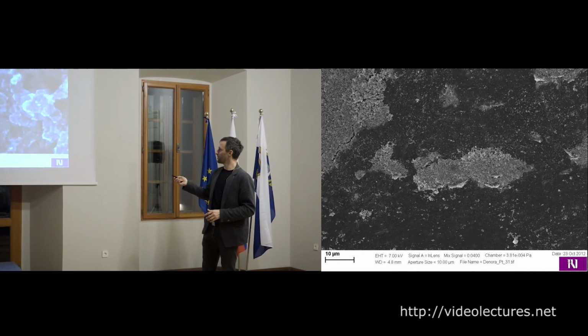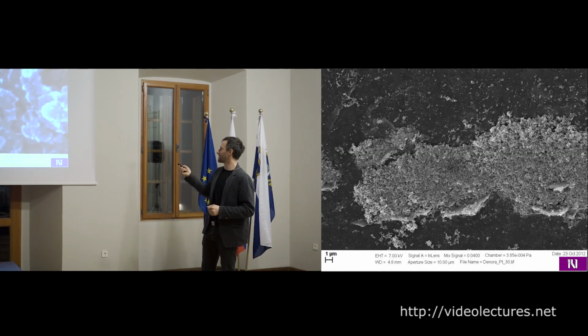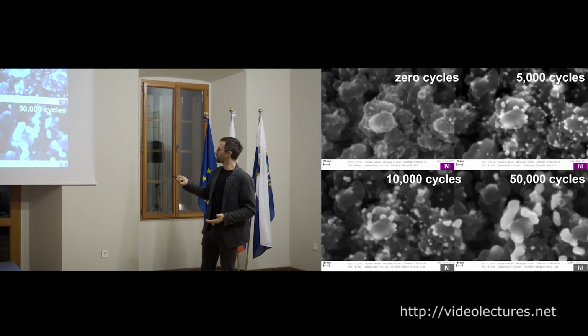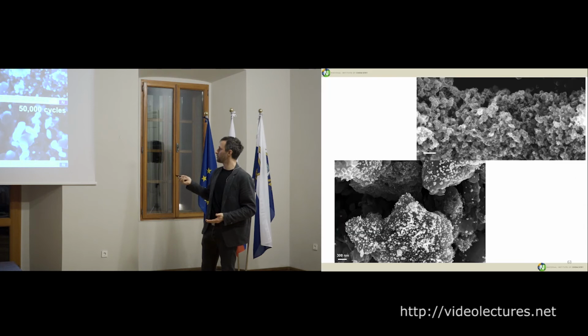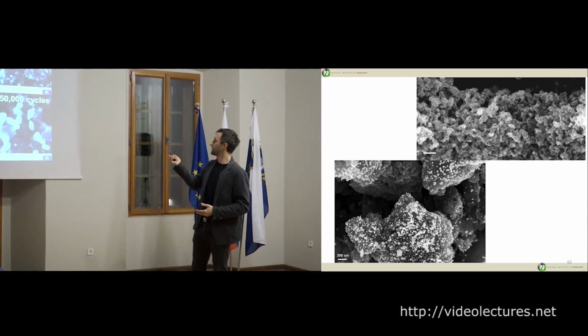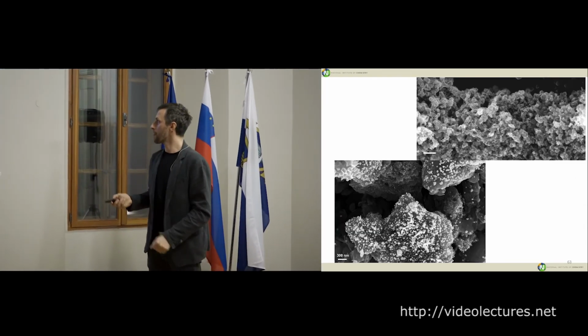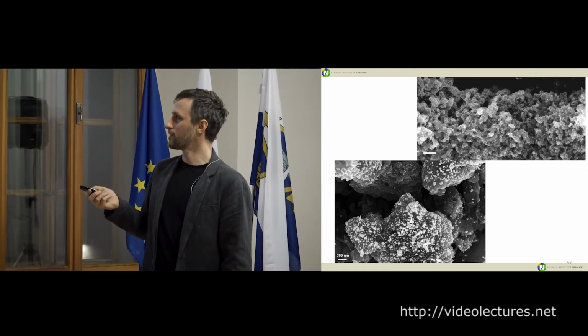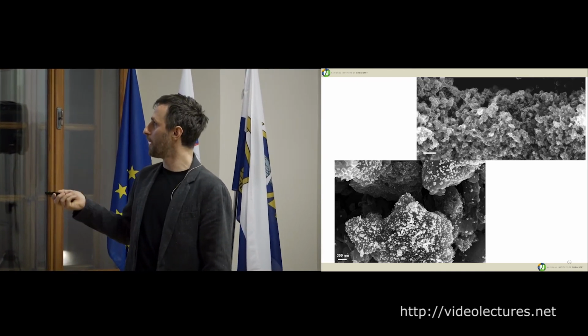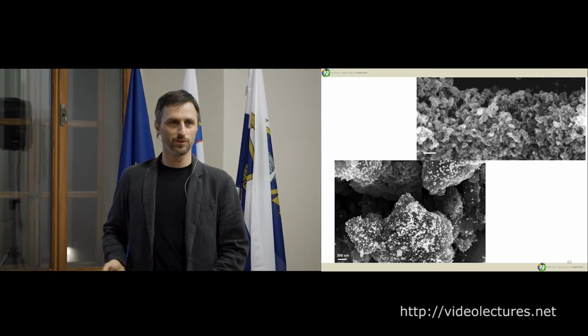Then you just zoom in, you have this path, and then in the end, it's kind of a high resolution SEM, but you see it. And then you just take consecutive images, and you just do this cycling degradation. Here something strange is happening because you see that the platinum is getting more and more, which is not logical.